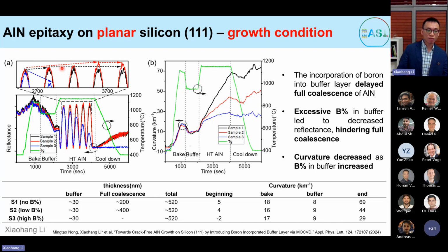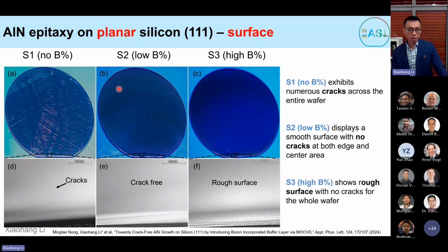However, from the left, you can see that when we have the most boron flow, the blue line, the surface becomes rougher and rougher. It's because the reflectance keeps reducing here. So we want to see how the sample looks from the crack perspective, but also look at the surface roughness, because you don't want cracks, but you also don't want a very rough surface. Because of the heterojunction we use in the devices, you want a very smooth and crack-free surface for the devices. So here are the surfaces of the 3 samples, 3 wafers.